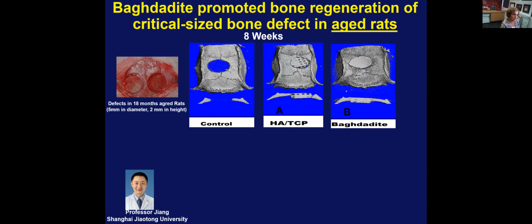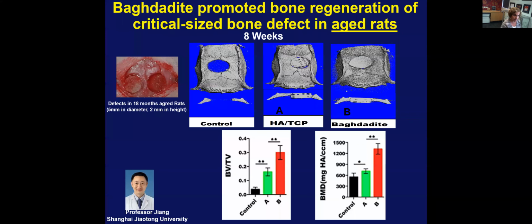And what you see here, this is the control. If left empty, nothing will generate. The hydroxyapatite tricalcium phosphate is the clinically used material, manufactured to the same standard here in the lab and 3D printed. Again, you can see a little bit of bone formation, but much more with our material, the Baghdadite, and this was validated when we measured bone volume to total bone volume and the bone mineral density. Red is our material, a significant increase in these parameters compared to the clinically available material and the control.